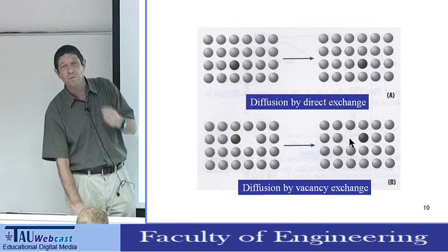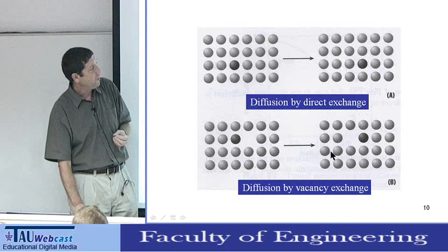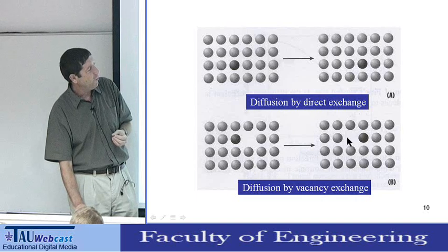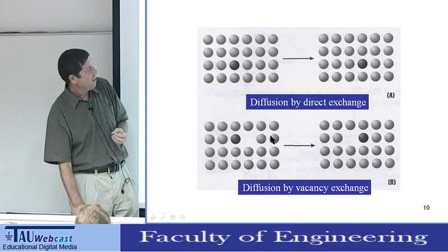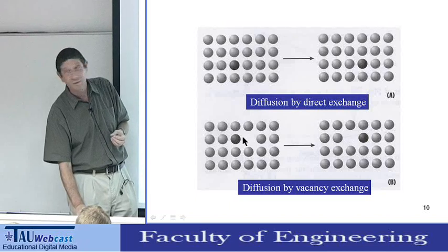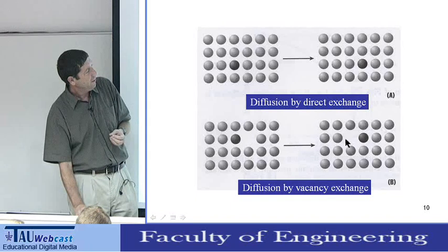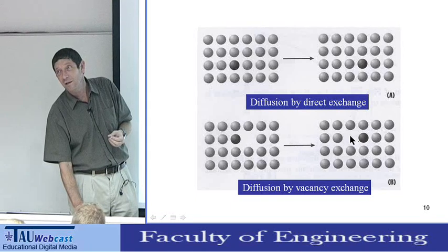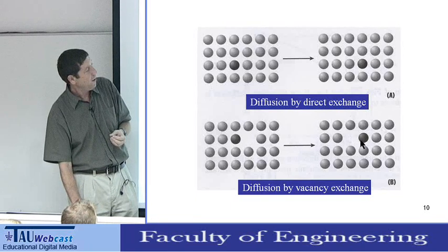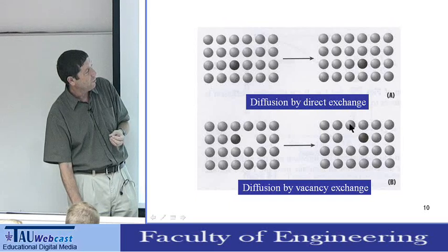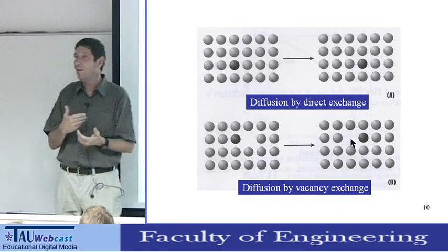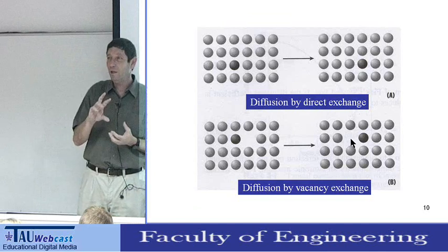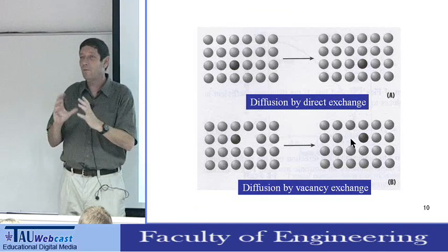There are four possibilities. One possibility is that this atom will move back, and then nothing will happen. Basically, this motion backwards will cancel this motion. Or this atom will move here, and then it actually will have a motion to the right of the black atom, or this will move here, or this will move here. So if you have four possibilities, one cancels the previous motion, and three actually keep the motion.